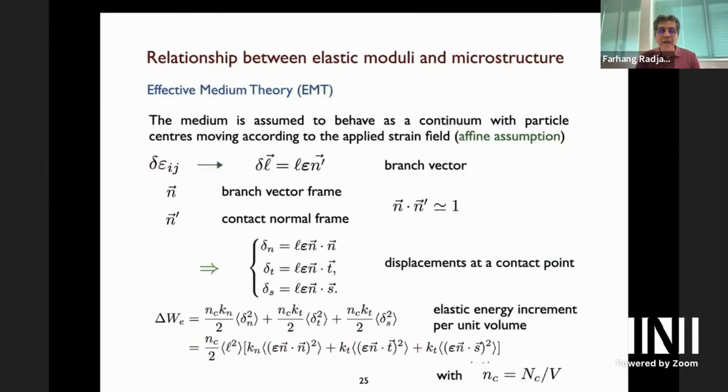And so they capture actually the strong force networks. The triple contacts are capturing most of it, and also double contacts. But still we have a mixture. And here the number of triple contacts is lower than initially. It's now 10% almost. So it was 0.14, now it's 0.1.